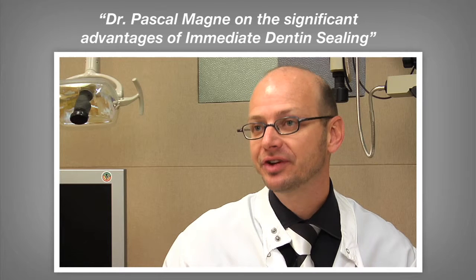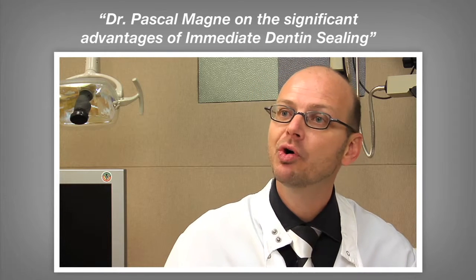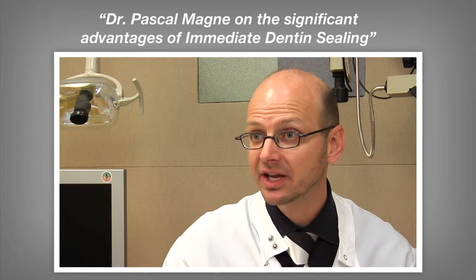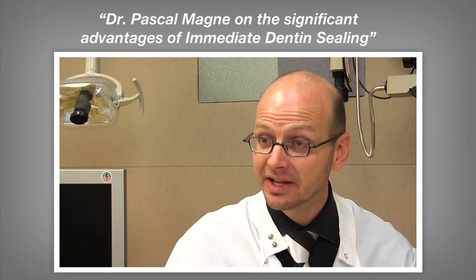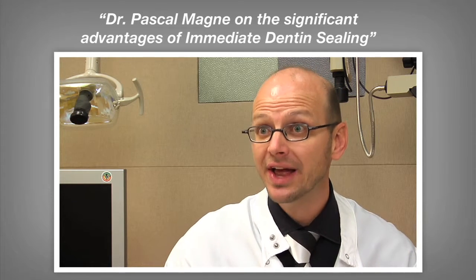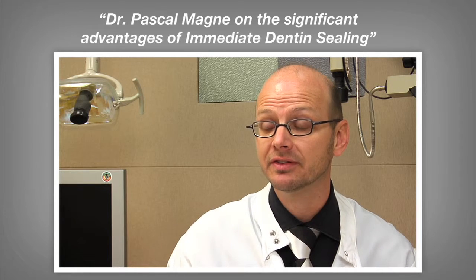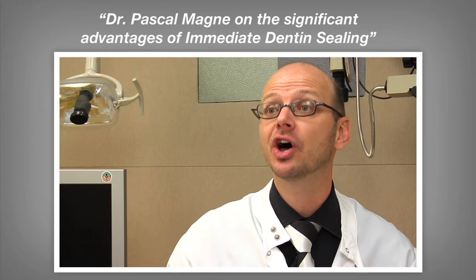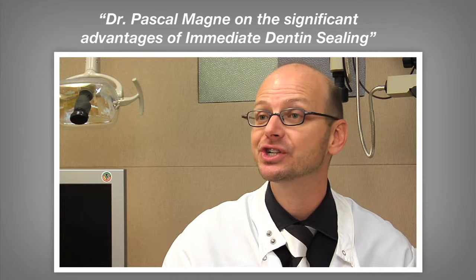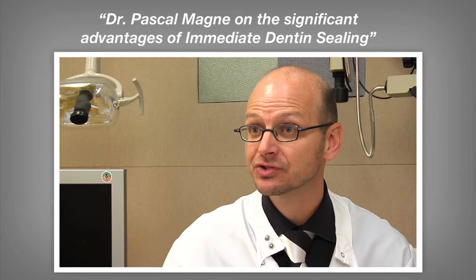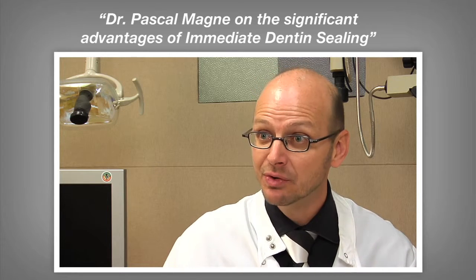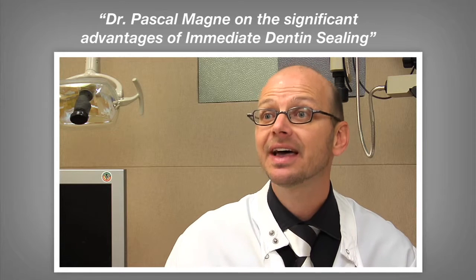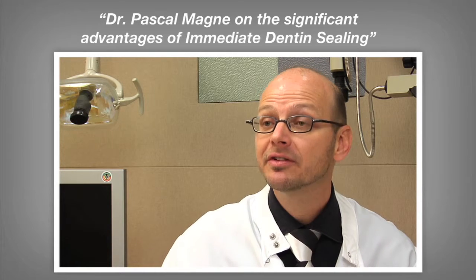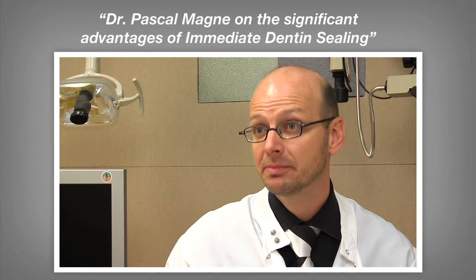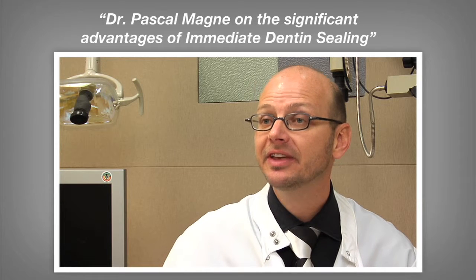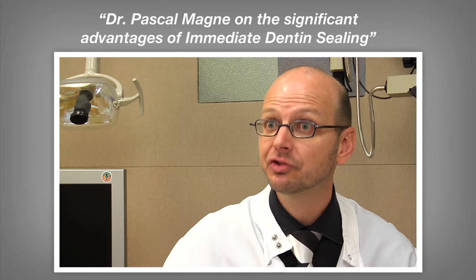Then there is a third point in favor of bond strength: because the dentin has been bonded earlier in the process, that is before taking the impression, when we reach the time of restoration delivery, which is finally going to cause stress on that bond because of the shrinkage of the luting composite, the good news is that this bond has been developed a week earlier, or maybe 2 weeks earlier, depending on how much time your lab will need to develop the final restoration. But as long as it is more than 24 hours, research has demonstrated that the delayed application of load to the bond is favorable and is going to maintain that bond in a better way. So delayed loading is inherent to immediate dentin sealing and will allow a better survival of that dentin bond.